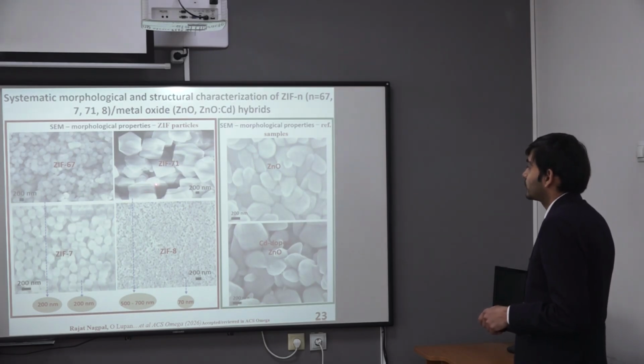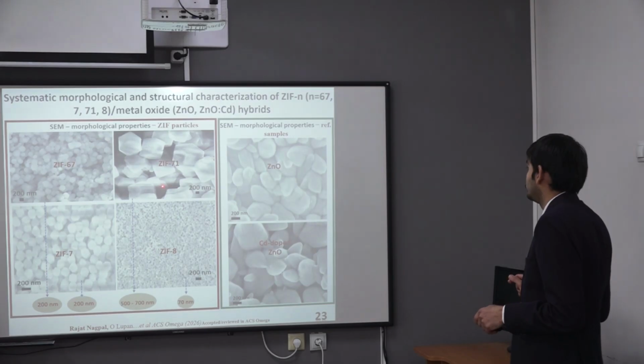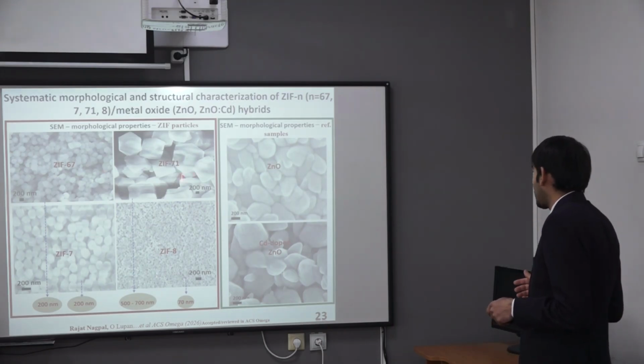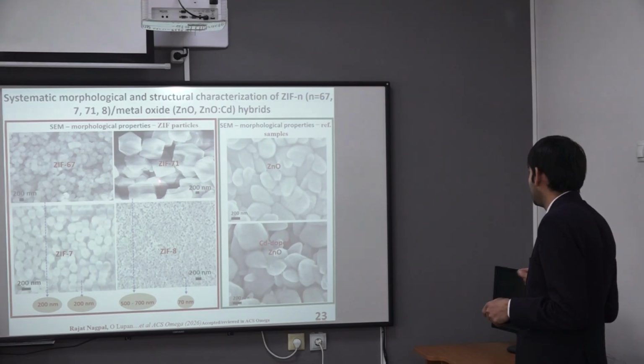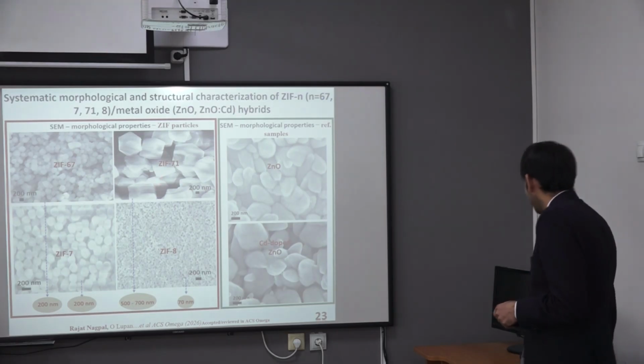So sometimes we have to use two different detector modes. For example, we made measurements at 15 kilovolts. Also we made a few measurements at 10 kilovolts. So it depends. If it is charging a lot, we have to interplay with the applied voltage.